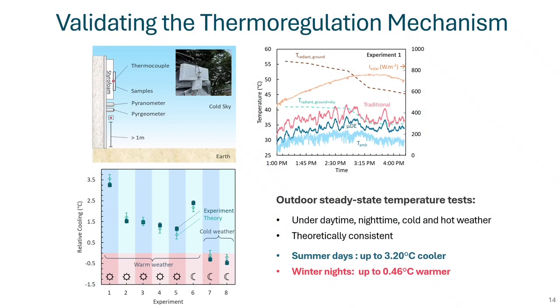We then validated the performance of the directional emitter under real outdoor conditions. We compared it against the traditional white paint as a reference. We first conducted a steady-state temperature test. The graph on the right presents experimental results under warm weather conditions, clearly showing that the directional emitter in dark blue consistently remains cooler than the traditional white paint in dark red.